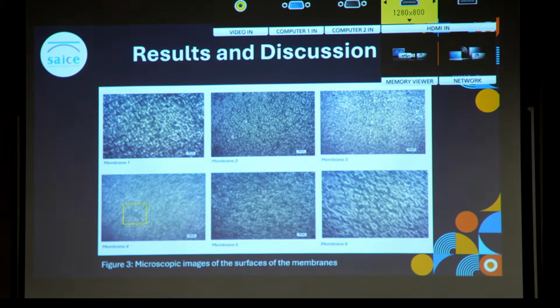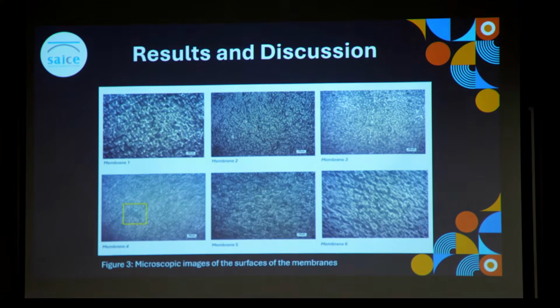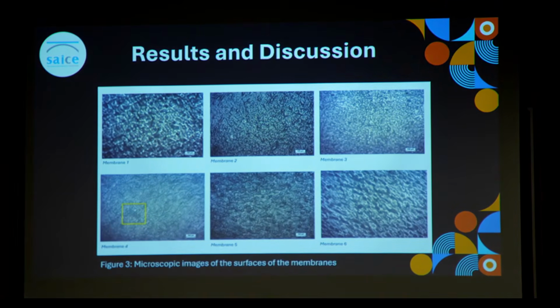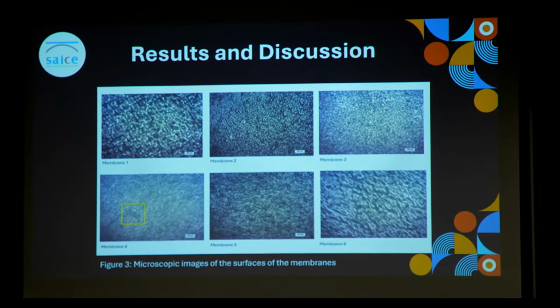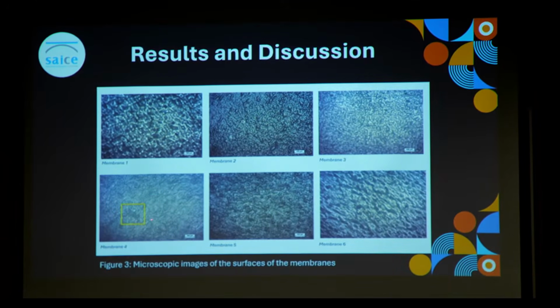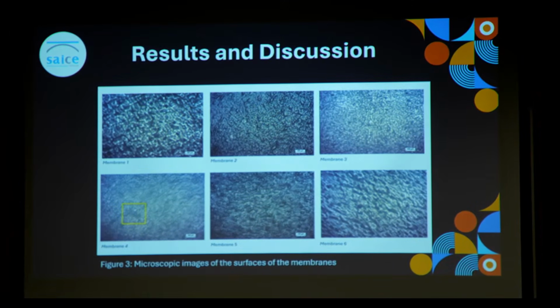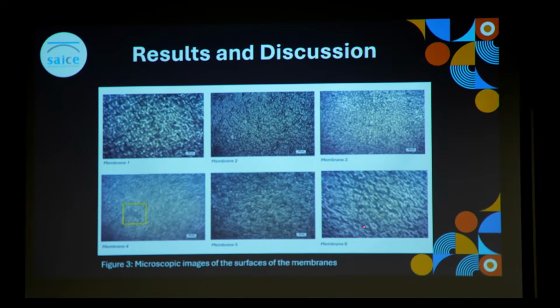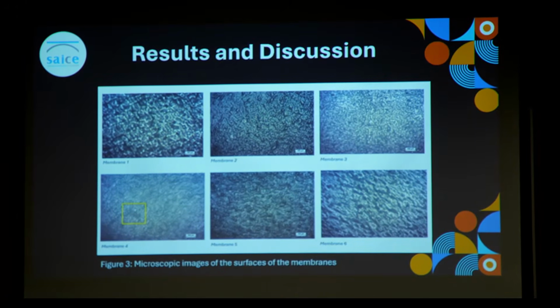Microscopic examination of the membrane surfaces showed that the addition of the PIL generally reduced the size of the openings, which enhances selectivity. A distinct defect was visible in membrane 4, where a large irregular opening suggested non-uniform interfacial polymerization. Such defects can compromise membrane performance by allowing greater solute passage. At high PIL loadings, as in membrane 6, the openings became larger, indicating structural instability caused by excessive PIL.